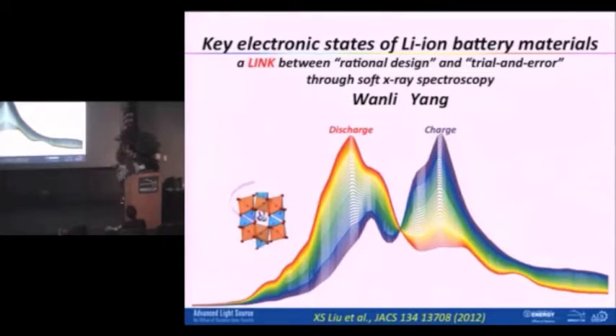What you are looking at on the screen right now is a battery cathode material, lithium iron phosphate. People expect that to be the next generation cathode material. When you charge this material, you pull the lithium out of it, and this is what you will see by using soft X-ray spectroscopy. When you pull the lithium out, you will see the spectrum evolve vividly from these red ones to these dark purple ones. And the evolution of this overall spectrum tells you a lot of things.